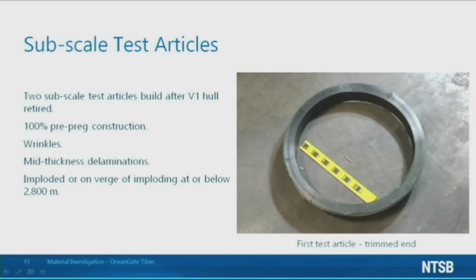After OceanGate retired the V1 hull, they manufactured two 1/3 scale test articles. Just like the Titan V1 hull, those cylinders were manufactured with extra material on both ends, and then the cylinder was trimmed to size. One of those trimmed end pieces is shown in this image, and in greater detail in these images.